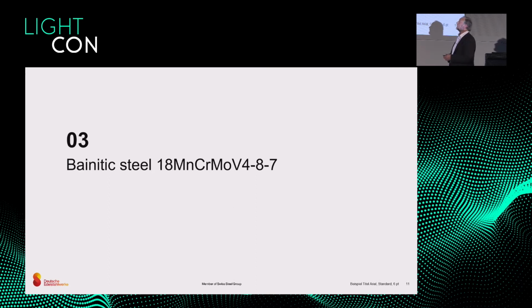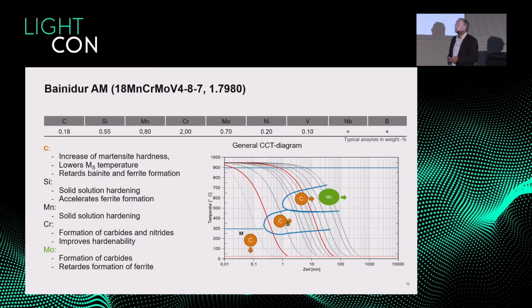That was the easy task. Now it becomes slightly more difficult. We use a bainitic grade. That's, I think, for most of you, hopefully not heavy metal. This is a CCT diagram. It's a continuous cooling diagram, as mentioned. We have a high temperature phase, we have a low temperature phase. And the low temperature phase, the properties depends on the cooling rate.